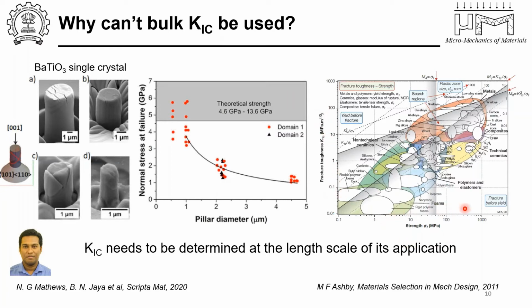Well, even at the macro length scale, it's not clear how the fracture toughness scales with, let's say, the failure strength of the material, because for a given class of materials, like the curves that you're seeing here, which are horizontal, there is no correlation, but there are some curves which are showing a strong correlation. For both these things, it becomes very hard to just predict from the yield strength what should happen to the fracture toughness of the material. So these are the reasons why we wanted to look at K1C at the length scale of the application of that particular device or structure.